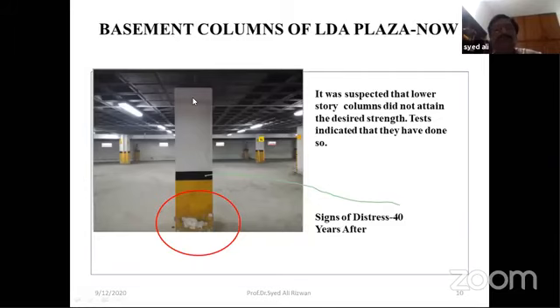And if you suspect segregation in a finished column, these tests are very useful. If there is a segregation, then there will be a tendency that the coarse aggregates, which are heavier, would be traveling towards the base when the concrete is fresh, before skeleton formation. And the rebound hammer, which gives you the surface strength, though it has some limitations, but then you